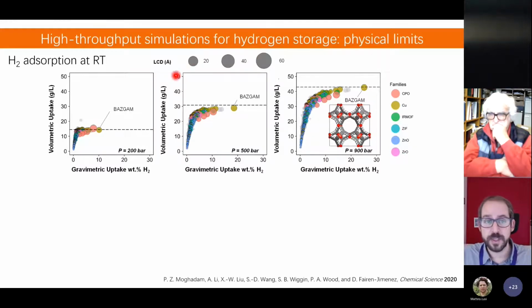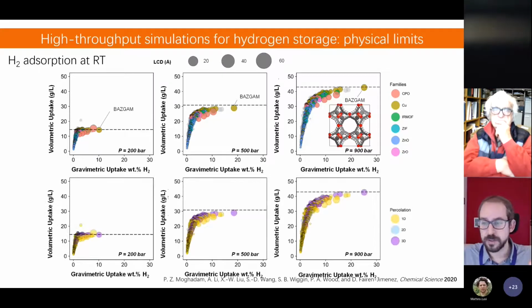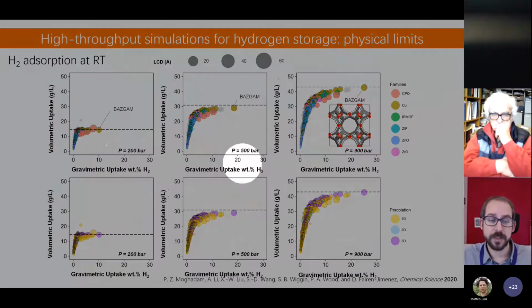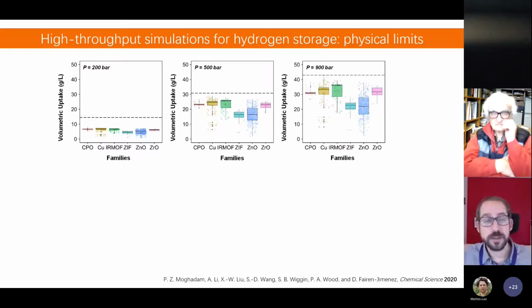The size of the symbol is related with the size of the cavities, and this allows us to really explore all the physical limits that exist in one specific application in gas storage. We can do this also looking at the percolation theory. So it's the way that the network is interconnected. If we have one-dimensional channels or three-dimensional networks, we can have very, very good description of what is really happening at different pressures as well, 200, 500, 900 bar. And we can identify the top material, which is this one that you can really see here in the screen. We can also apply some statistical information, try to really understand the dispersibility of the data.